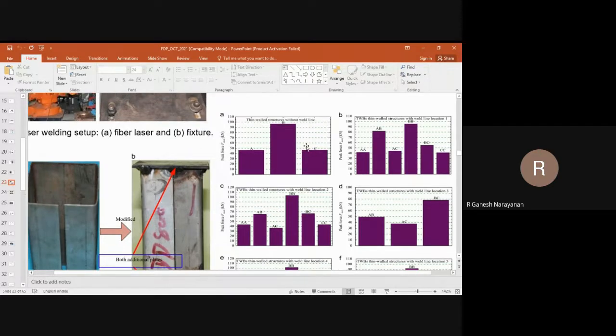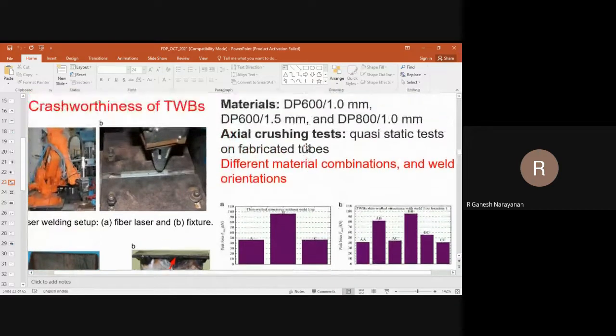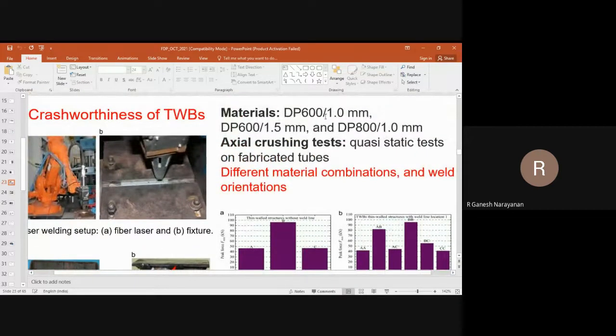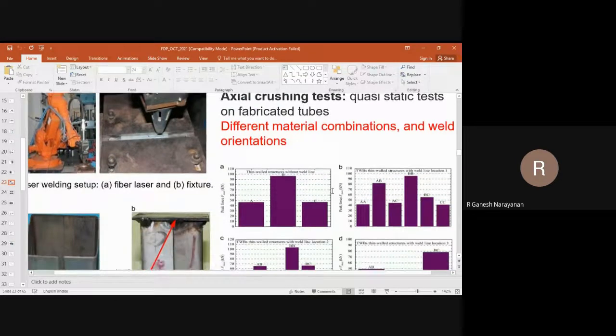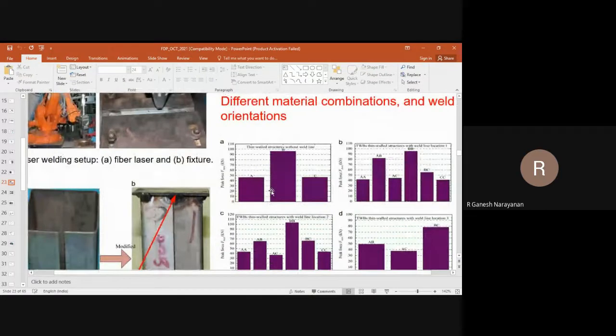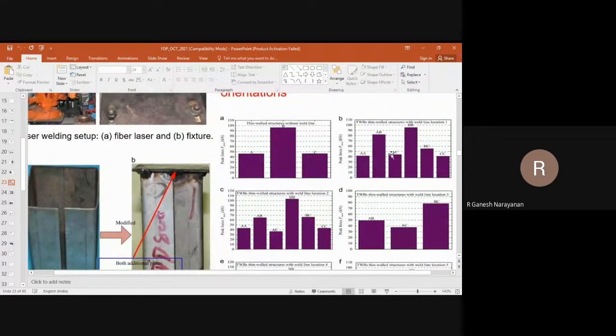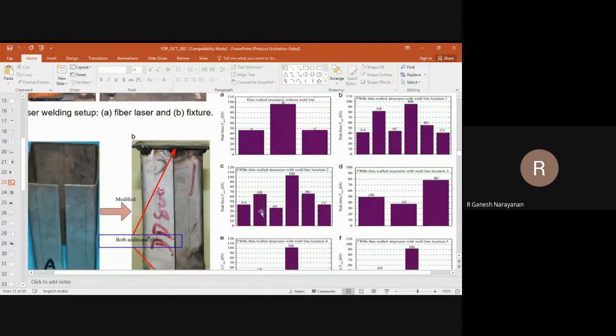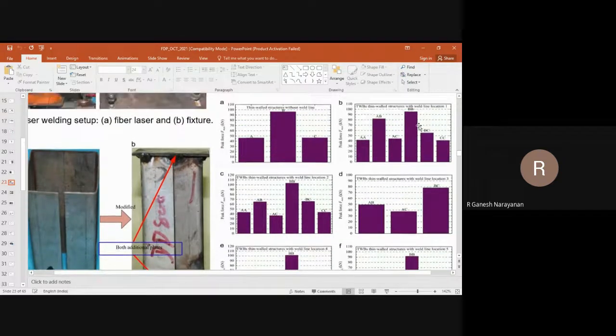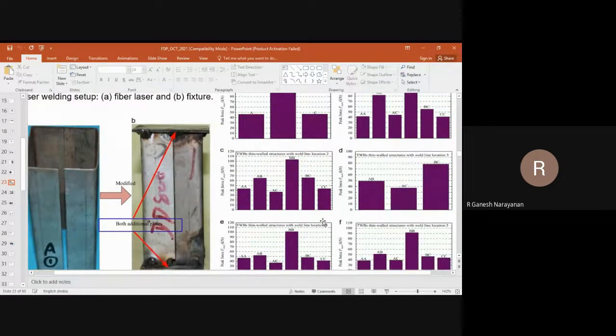Okay, A is for one particular welded blank. Let us say DP600 1 mm, DP600 1.5, DP800 1 mm. A, B, C you can keep. And you can see the peak force during that axial crushing test is this much. Different combinations: A, B, A, C, B, B, C, C, C. This is with weld orientation or weld location 1, weld location 2, weld location 3, and different combinations. All are possible, and they have evaluated the peak force.